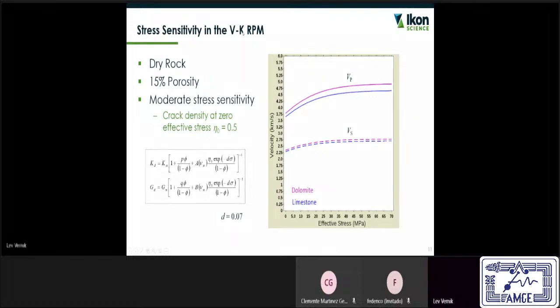Now, the VK model, as we refer to it, also allows you to model the stress dependence of your rock. That is very significant in 4D applications, or even in exploration when you are trying to extend the depth of exploration without having any logs, without having a nearby wellbore where you can calibrate your model. And so this stress dependence here is hidden in the crack density curve. So why is that the case?